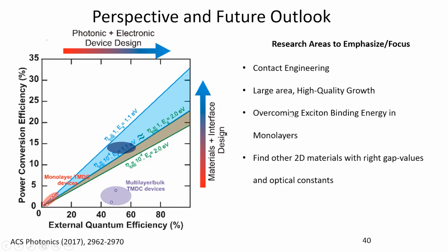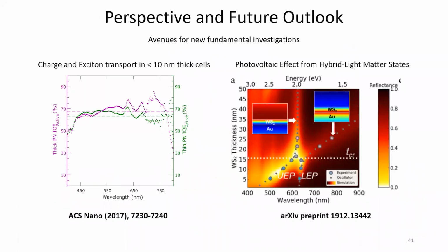And then, of course, this big challenge is overcoming the exciton binding energy in monolayers, which very few people have thought about, and what consequences it would have on the absorption and optical constants if you reduce the exciton binding energy. And finally, of course, the room is open for discovery of new two-dimensional materials with the right band gap values and optical constants. There may be others out there that we don't know about that are better than these 4 semiconducting TMDCs we talked about. Finally, there is also some room for new fundamental investigations.